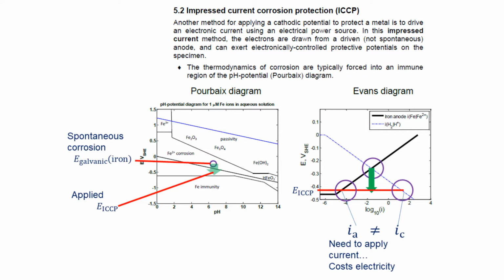We might even want to try and push the metal just slightly into the immune regime so that there's basically no corrosion. But we wouldn't want to push the potential to any more negative a value, because any more negative surface potential provides no further slowing down of the iron corrosion, but it does continue to provide an increase in the rate of hydrogen evolution from the unbalanced cathode process. And that would simply increase the amount of electricity we need to supply and increase the cost of operating the system without providing better corrosion protection to the iron.